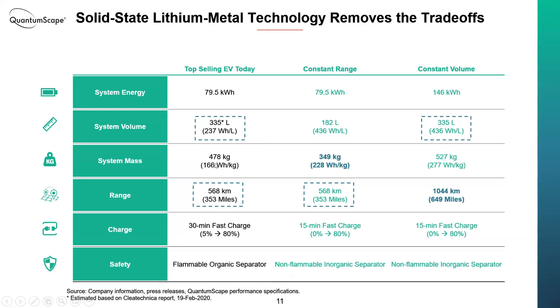It weighs a little over 1,000 pounds, or 478 kilograms. Can drive 350 miles roughly, and that's with really good engineering of the system. Charge time, it says 30 minutes here. I think more like 40 minutes is more what we see. And then of course it still has this reactive liquid electrolyte. If we take the same basic system design, but we replace it and use a solid state lithium anode, there's two things we can do. We can either maintain the pack size, so still 80 kilowatt hours, but ultimately have less space taken up by the battery.